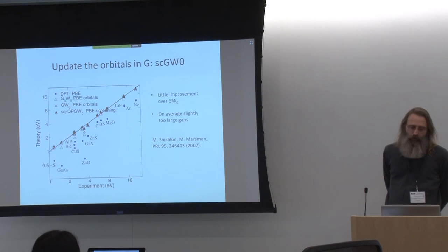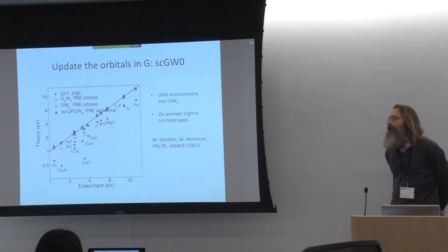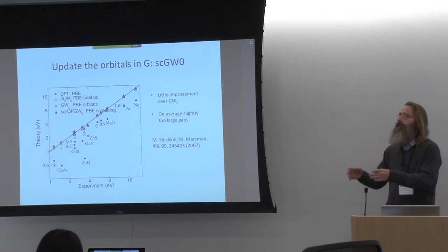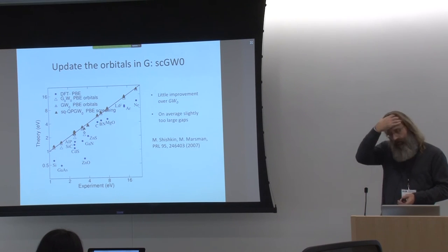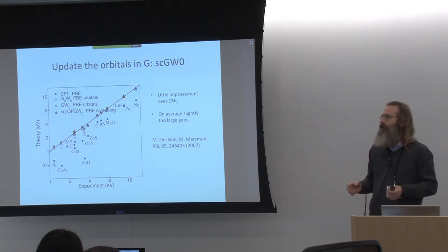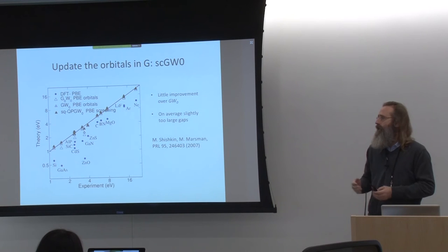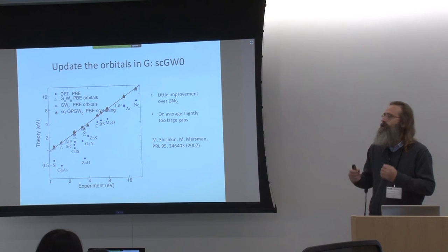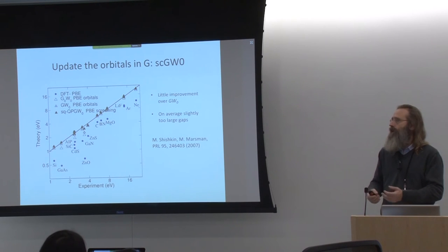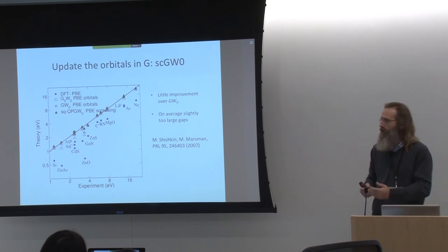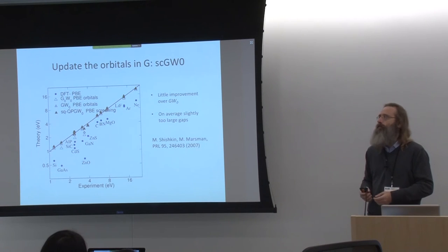No, and that goes back to exactly the same point made before, that this combination of random phase approximation and DFT input match as well. Only when your system at the DFT level is really, really horribly described, it pays off to do something like an HSE, a hybrid functional calculation, and G0W0. So don't update anything there. Then you can do a single shot GW calculation on top of it. So for instance, if you have something that in DFT is a metal and definitely should not be, then it might pay off to start from a hybrid functional, but you wouldn't want to do anything beyond single shot GW on top of that.